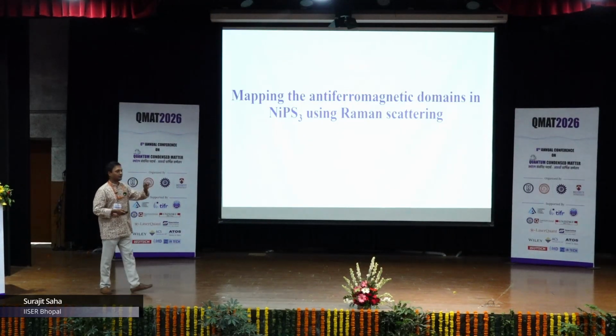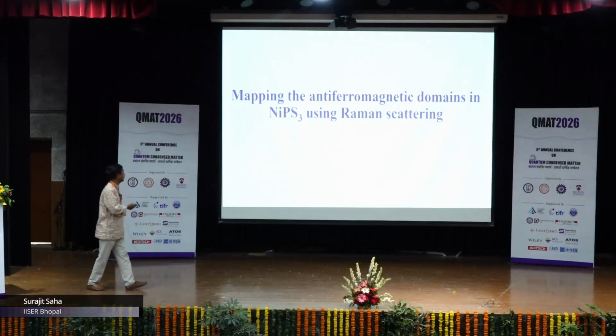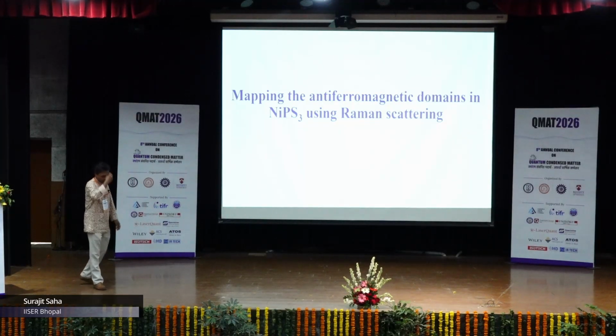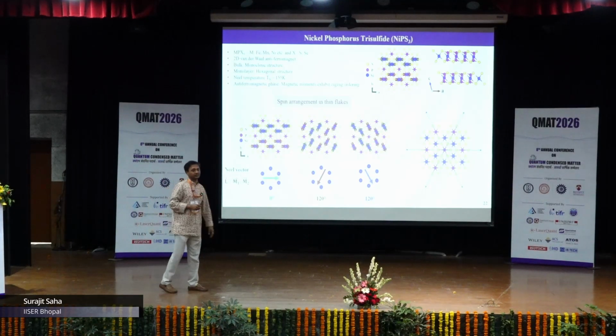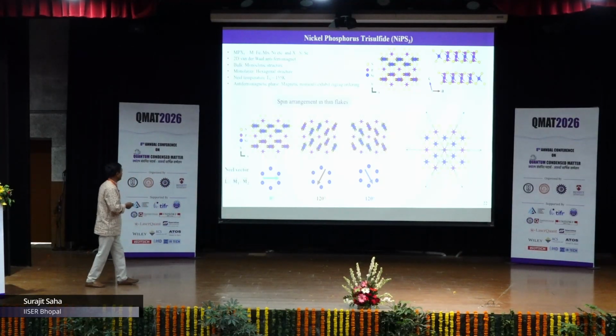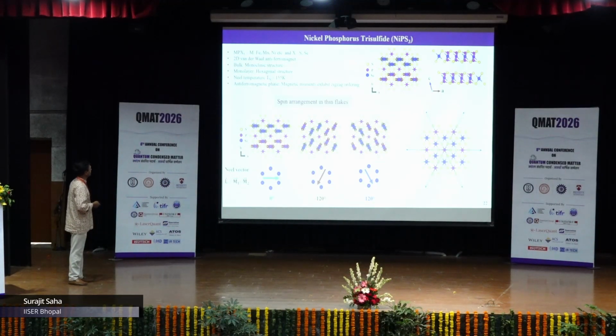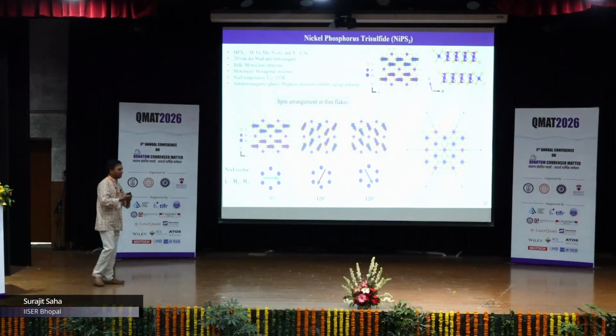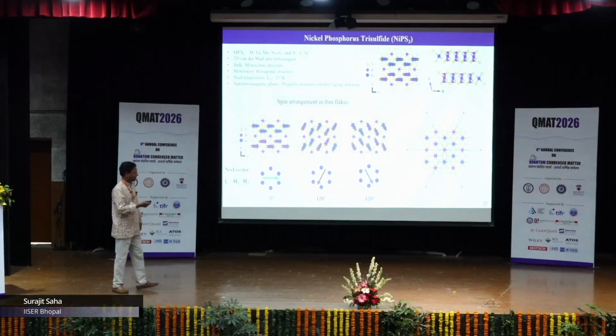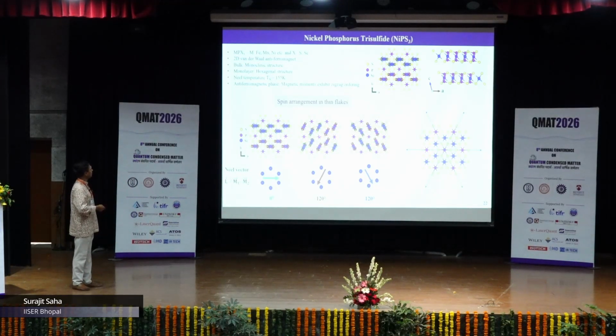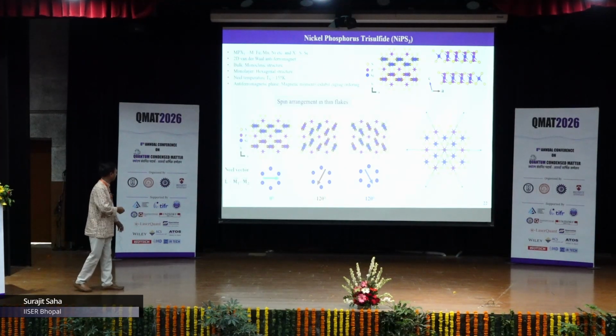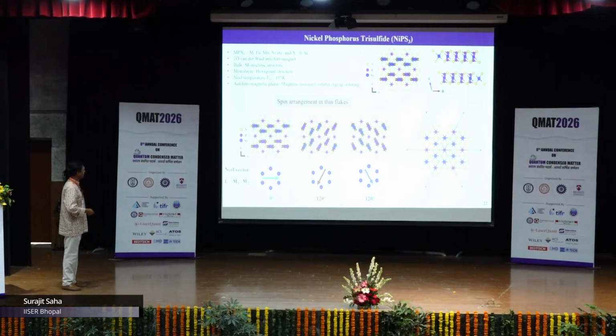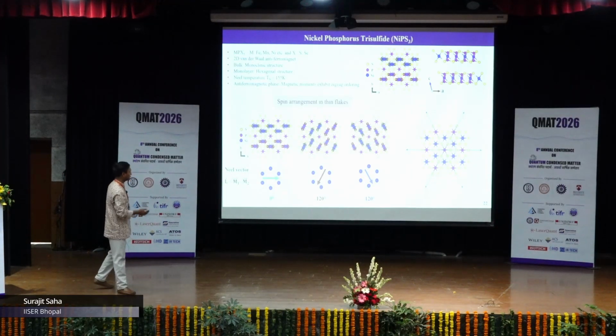If I have about 3 minutes, then I can quickly talk about what we actually looked at in NiPS3. In NiPS3, we know at low temperature it is antiferromagnetic. In the antiferromagnetic ordering, as you can see, the spins are shown in the red and black colored arrows here. They are in a zigzag chain, anti-parallel to each other. There are 3 possible configurations that it can take. If I draw this Néel vector, I have this horizontal 0 degree orientation, and then 2 other orientations which are 120 degrees from each other.